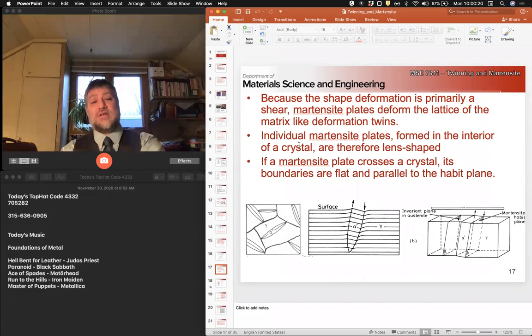So we have this shape deformation in Martensite, this large shear. So we end up with shapes that look a lot like deformation twins. Okay? These lenticular shapes come about because this is what minimizes the elastic strain energy. In a graduate class or in a mechanical behavior class, we talk a lot about that strain energy minimization, but it's not super important for the purposes of this class. But Martensite near the surface actually causes surface relief, due to this shear.